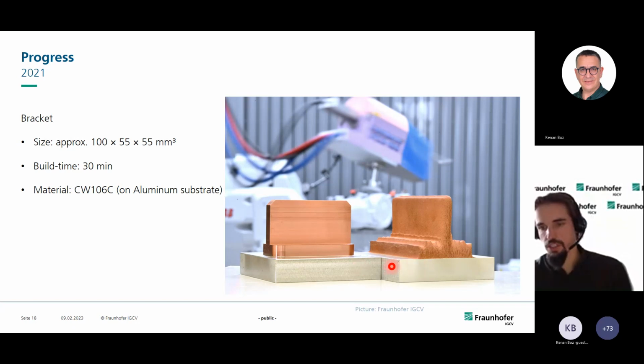But what still needs to be done is to identify suitable strategies to be able to build up within a sufficient angle to the build plate. So this is rather tough. You need a very good robot path planning strategy to get rectangular edges with this process. Otherwise, you always get just a Gaussian-like shape of your parts, and need to mill away very much of your deposited material afterwards. And yeah, as you can see, it's very fast. The build time was here only 30 minutes. And this is a copper chrome zirconium built on an aluminum substrate.